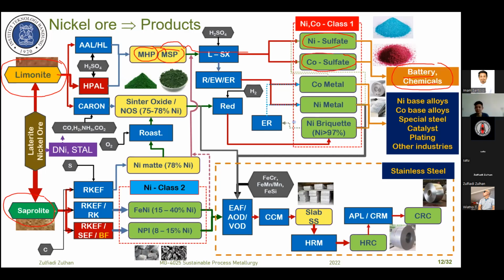And for saprolite nickel ore, the current or common technology is RKEF. We can process the saprolite nickel ore into nickel matte. The nickel content is around 78%. This nickel matte can be processed further to produce nickel sulfate, nickel oxide sinter, or nickel briquette, nickel metal, and we can also recover the cobalt from the nickel matte.